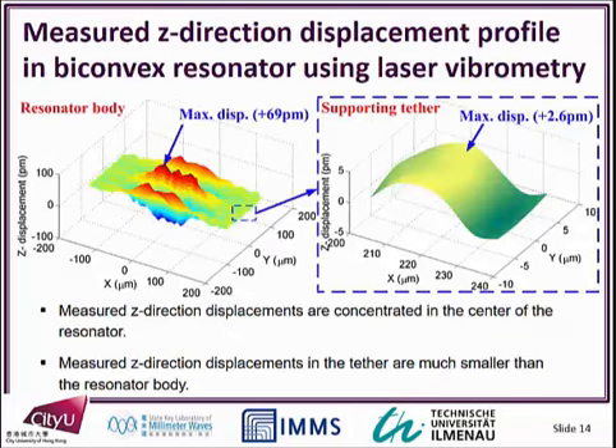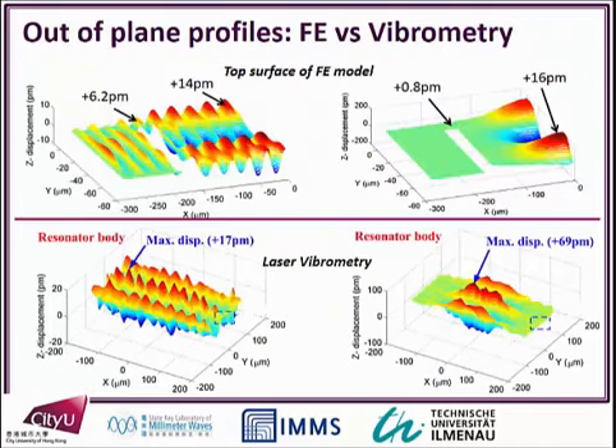Now we do a scan on the one with the curved edge, and we see there's a difference because it's concentrated right in the center. When we scan that surface over there, you see about 2.6 picometers. It's a huge difference compared to what's concentrated at the center. To summarize, that's what we simulate in FE, and that's what you measure in the vibrometer measurements, and you see it's almost like a copycat of each other. You see these ridges down here, you also see these ridges down here, and you see your concentrations in the middle.